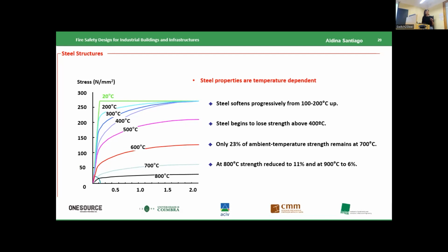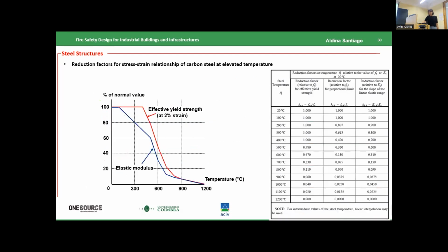And normally, the temperature in a fire in this kind of building is around 1,000, 1,200, or less. So these temperature values are the normal temperature in a fire in a compartment like that. And the steel melts at around 1,500 degrees. I have here also the comparison of the degradation of the yield strength with the elastic modulus. The stiffness reduces much faster.